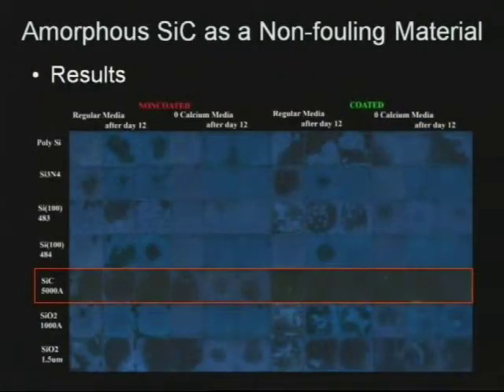And then for the last minute or so, I'll draw a link back to the silicon carbide research we do here at CASE by saying that I was inspired by my colleague's work in silicon carbide and thought there would be a play here on the bio side. Most of our materials and biomedical microdevices can't tolerate the high temperatures that one would use to grow the high quality single and polycrystalline material for the high temperature MEMS. So we switched to an amorphous phase of silicon carbide, which can be deposited at temperatures from about 30 degrees C up to 400 C.